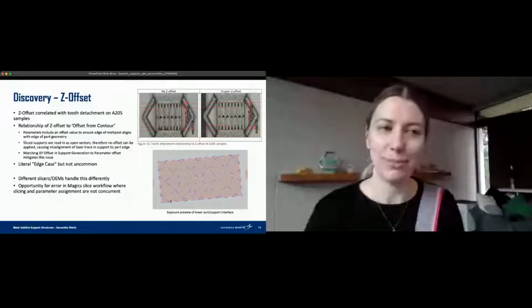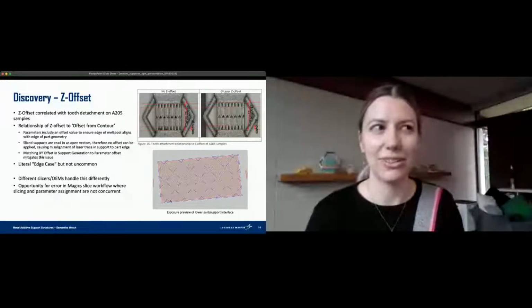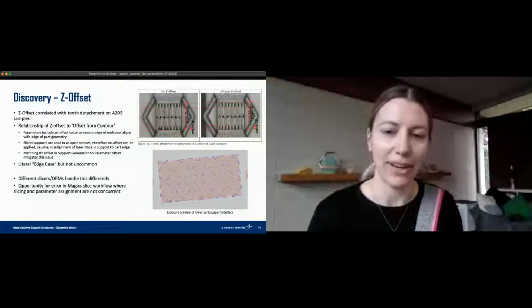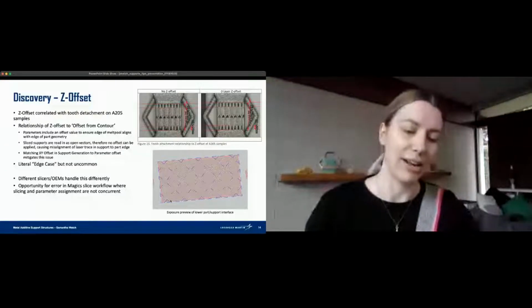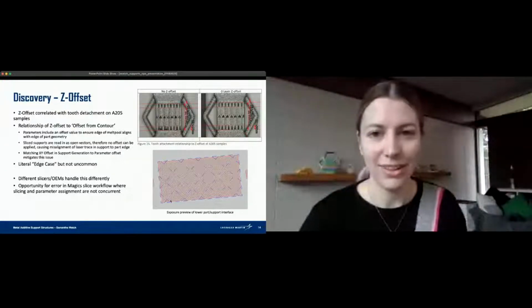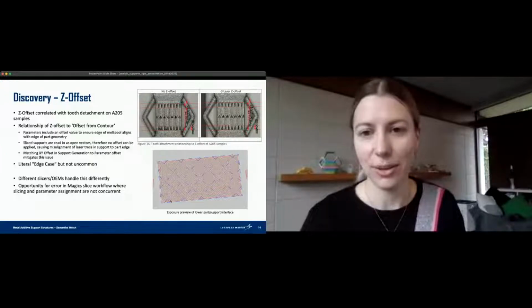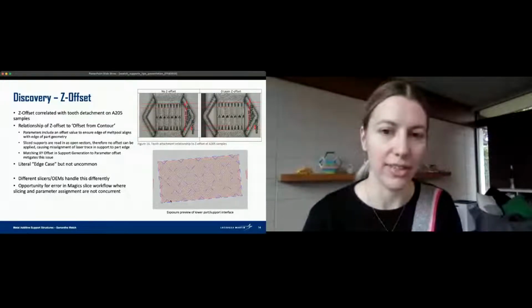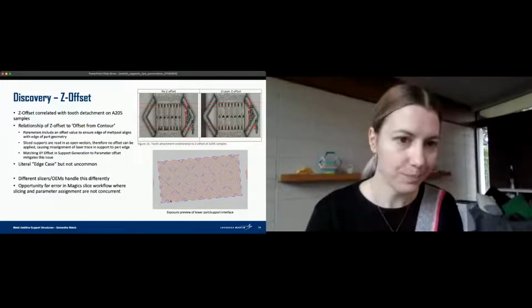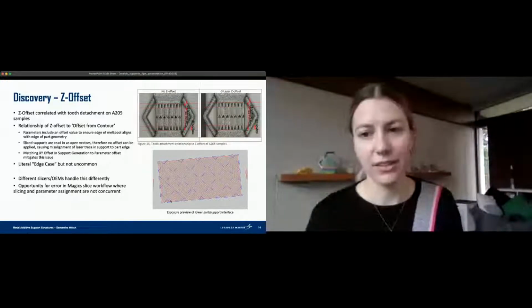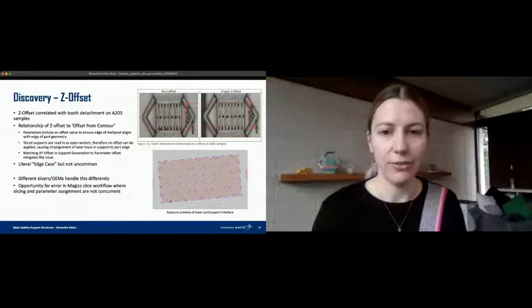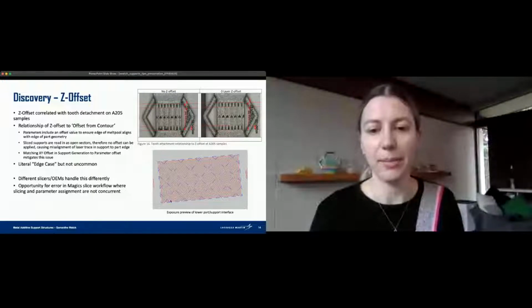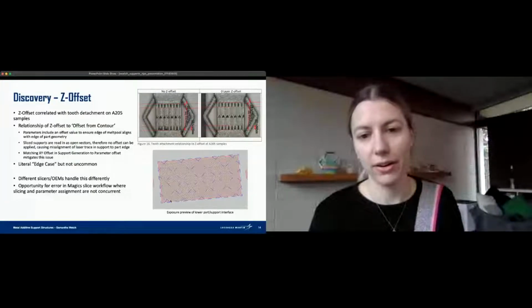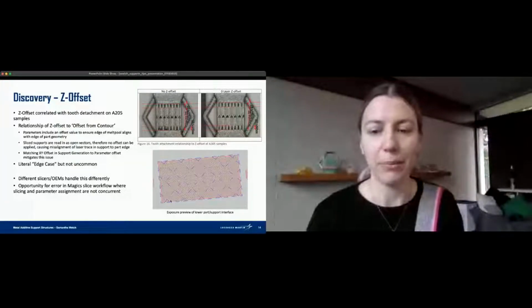When I slice my supports, they're all open vectors. There's no way to apply that offset to an open vector. And so they were actually being projected outside of my part lines, which is not what I was intending, and something that was detrimental to the strength of the samples where that was present. So there's a fix for this. If you shrink your supports down to the same extent as that parameter offset, now it's going to line up where you think it will.